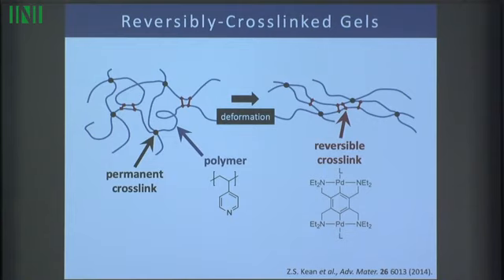And then we throw into the solution phase of the gel reversible cross-links. These things right here are called Van Koten complexes. They are characterized by transition metals that can form up to two bonds with the nitrogen on the poly-4-vinyl pyridine monomers. You can tune the binding strength of these Van Koten complexes by changing the organic scaffold that surrounds them. Okay? The important thing is that these bonds are reversible because they're transition metal bonds. And that will be important for the functionality of these systems.